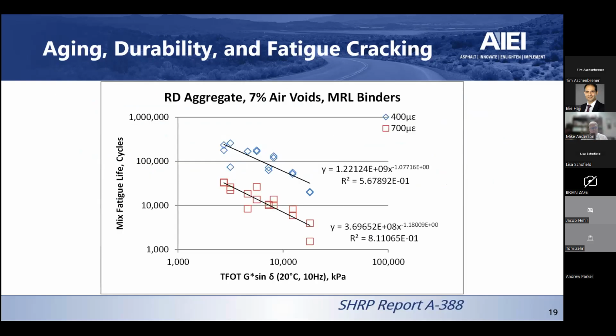If you look at the data that you get out of SHRP Report A-388, which was looking at laboratory fatigue performance of asphalt mixtures, and you plotted their data, they did what I think was called an 8x2 study, if I remember correctly, where they used 8 different core asphalt binders and 2 different aggregates. They actually used 2 different air void levels, 2 different strain levels. So a variety of conditions in there.